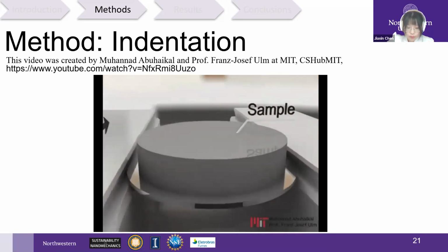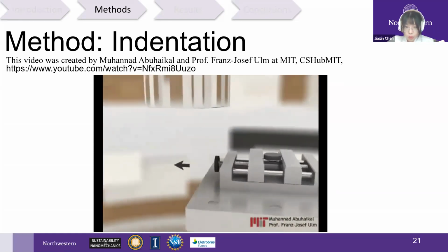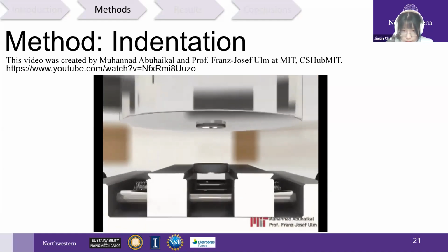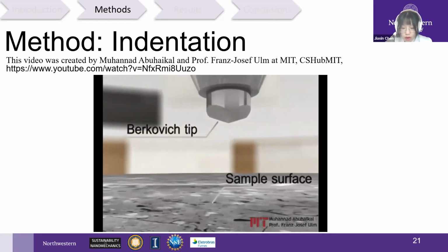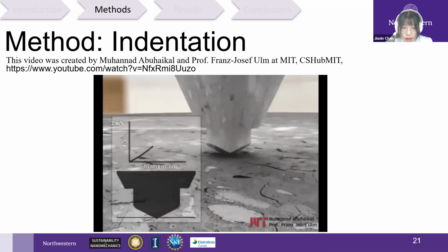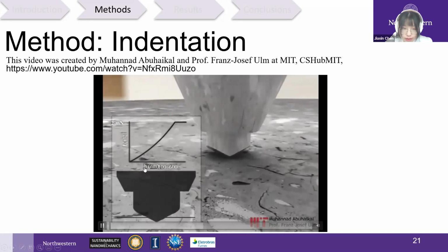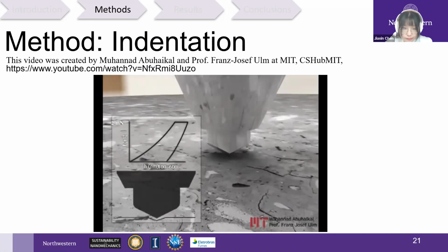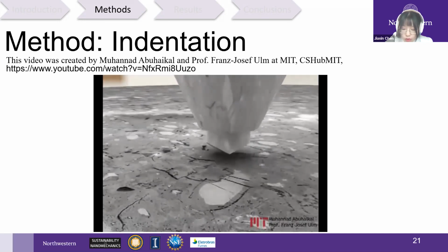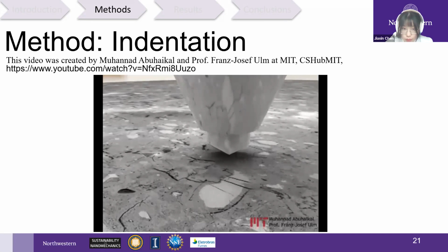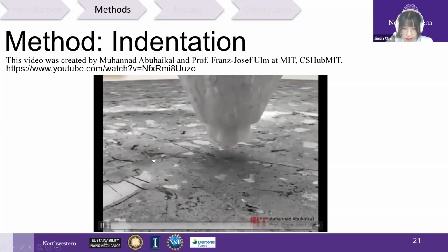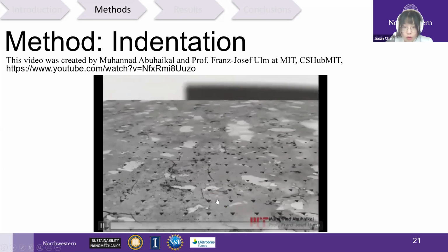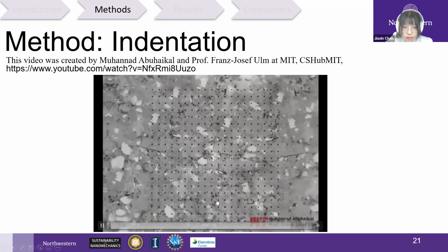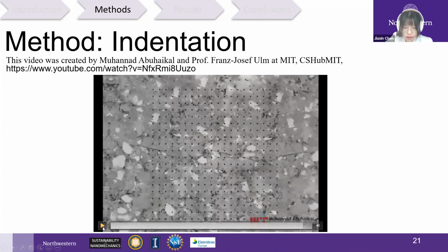Here is our sample and the sample holder. When we begin the indentation test, the sample holder goes up and the indenter goes down. The Berkovich tip is pressed into the sample surface, and we get the force and penetration depth. We can also set up a grid indentation automatically, as shown here, the first one and the second one. But we have a spacing which is 3 times the penetration depth to avoid overlapping. Here's the grid indentation result.